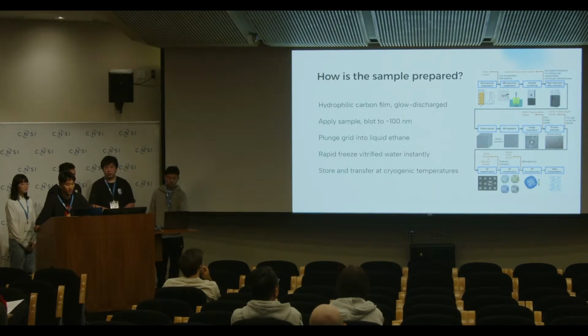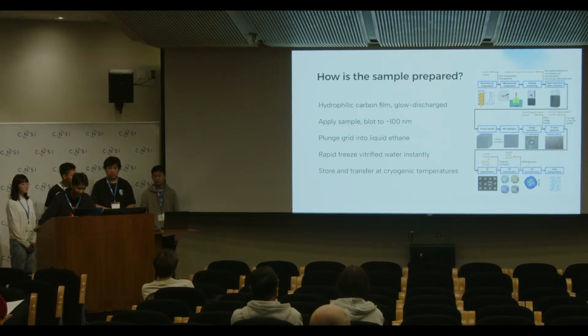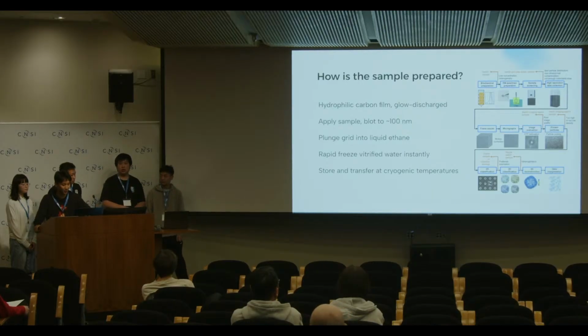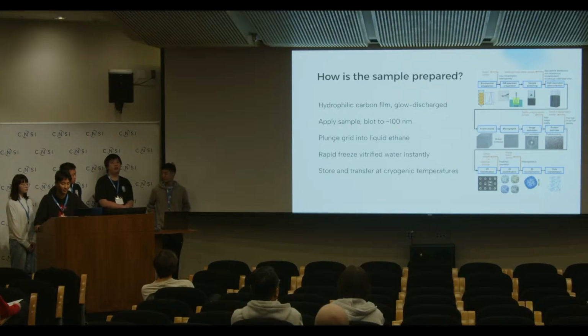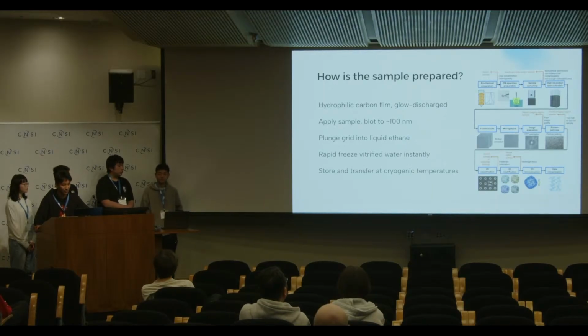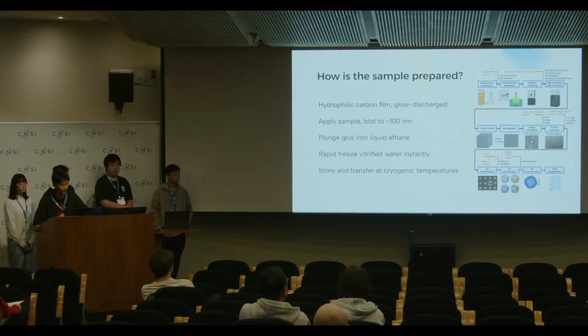Because the remaining film is so thin, under 100 nanometers, and the cooling is so fast, on the order of 10 to the power of 5 degrees Celsius per second, the water in the film solidifies into glassy ice instead of forming damaging ice crystals. The grid is then stored and transferred at cryogenic temperatures, around minus 170 degrees Celsius, which maintains the glassy state and locks the sample in place.